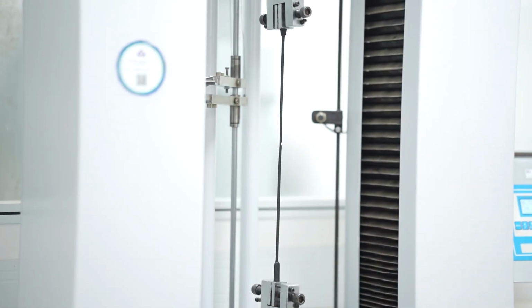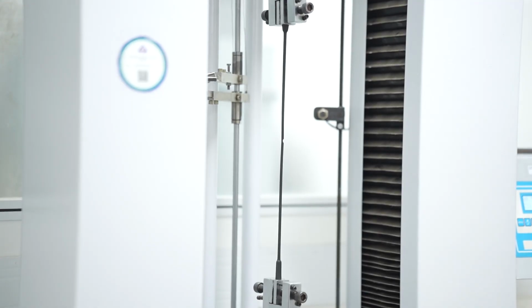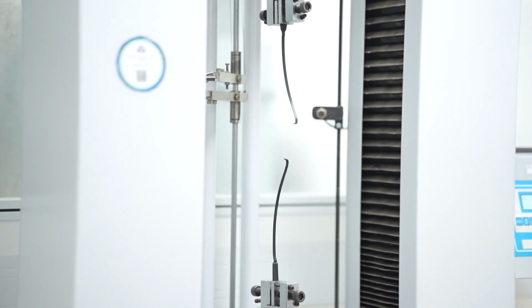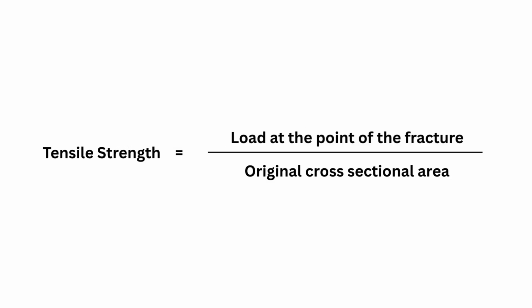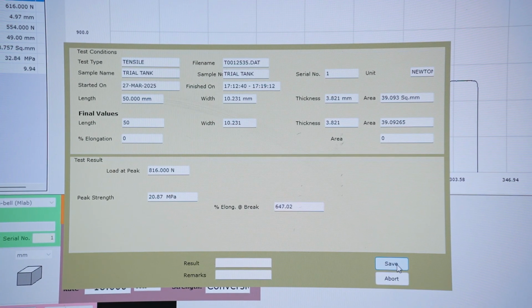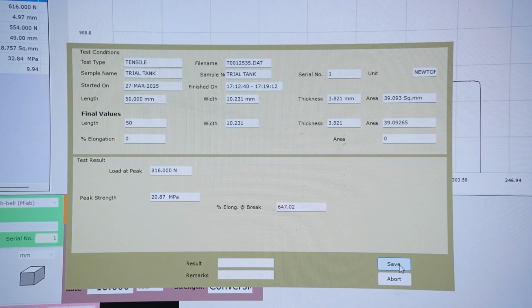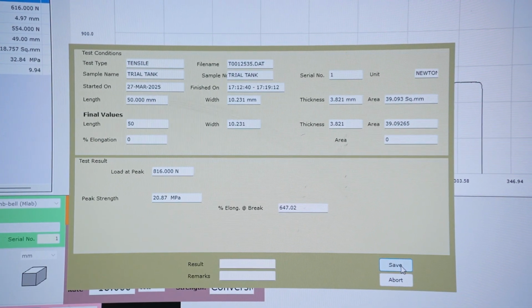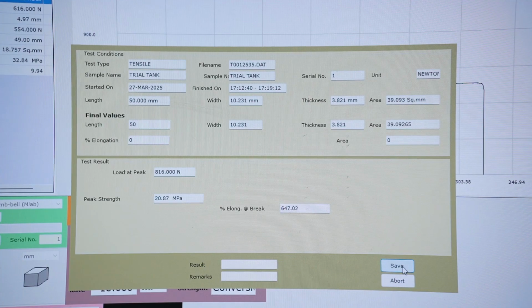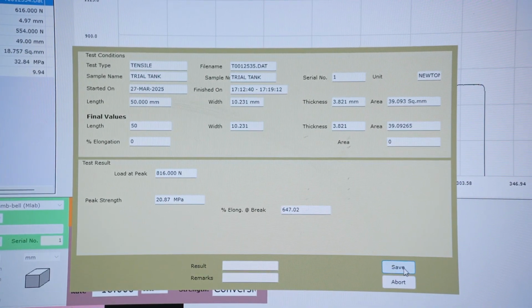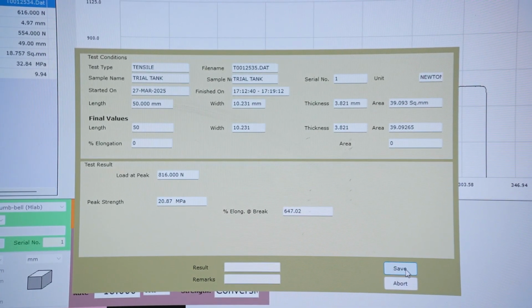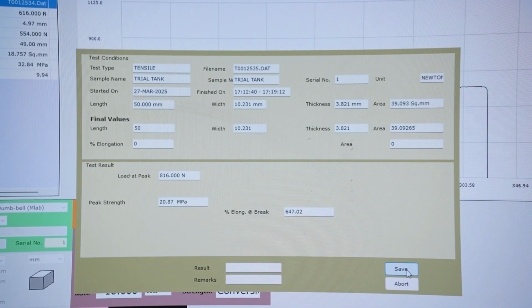The specimen is mounted on the machine and load is applied until fracture. The tensile strength is calculated by dividing the load at fracture by the original cross-sectional area. The test is conducted on specimens and the average tensile strength is taken. The required yield strength and elongation at break should not be less than 15 megapascal and 350% respectively. The next test is the reversion test.